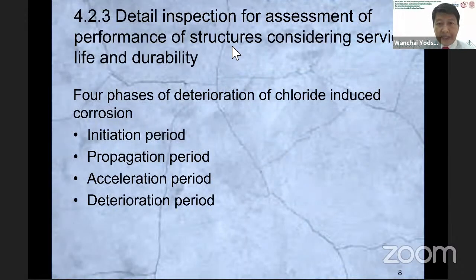For the detailed inspection for assessment of performance of concrete structure considering service life and durability, we have four phases of deterioration of chloride-induced corrosion. In this standard, it is separated into four phases. The first one is the initial period. The second one is the propagation period. The third one is the acceleration period. And the last one is the deterioration period.